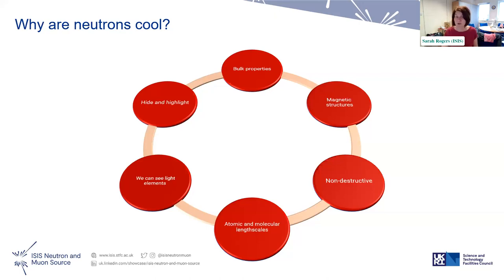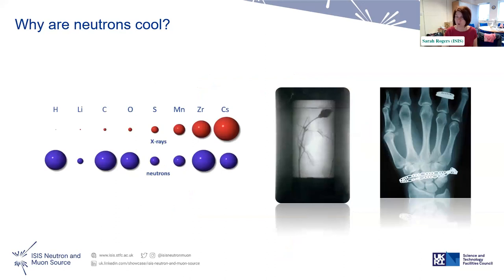So to go a little bit more into this neutron cross-section, I'm sure you're probably aware that it's very different to what you get from X-rays. So X-rays is the top, the red line here, where the light elements, you hardly get any scattering. The heavier the element, the more the interaction with the X-ray. I think everyone's very used to the classical X-ray image of a hand, where the squidgy hydrocarbon parts of the hand are invisible, the skin, the flesh, the muscle. But the heavy elements, the bone, the calcium and the jewelry, they interact very strongly with the X-rays.